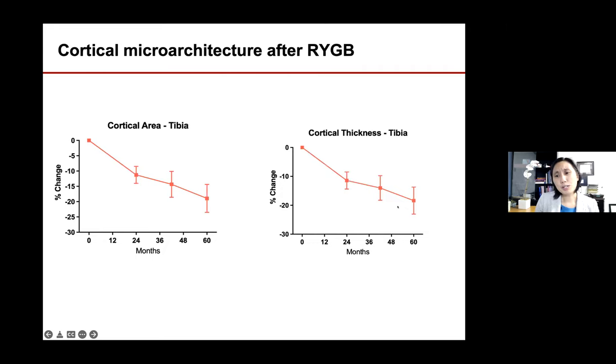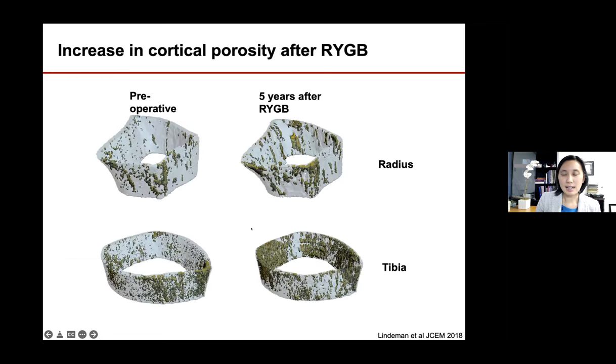In terms of our HR-pQCT findings, here are data from the same cohort over a five-year period, and we did see indeed declines in cortical area and cortical thickness at both the tibia and the radius over the course of the five-year study. But unlike what you saw with DEXA, there is a continued bone loss throughout the entire 5 years of the study that is relatively constant, and that's seen in some of our other parameters as well.